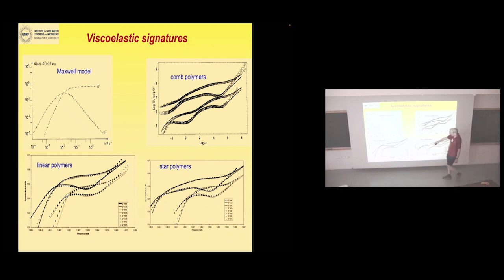So this is what one finds for very long entangled linear polymers. These are 2 different lengths. Down here, it looks like a Maxwell model. In here, the G prime is basically independent of frequency. So over here, it's behaving a lot like a rubber. This is silly putty in the rubbery regime. But eventually, at high enough frequencies, you start seeing this turn up again.